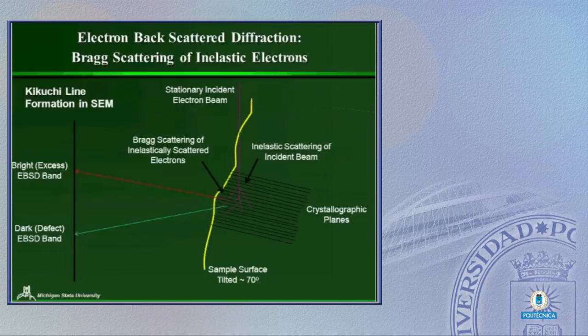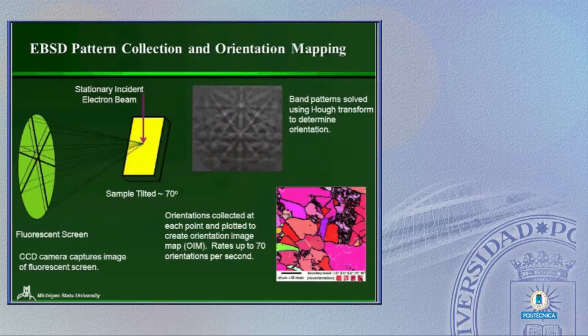So the idea with electron backscatter diffraction is we have a sample tilted to a fairly large angle. We have an incident stationary electron beam. We get inelastic scattering in the sample. And those inelastically scattered electrons diffract to form Kikuchi lines that we detect on some sort of a screen. And so the idea is you have a sample, again, that's tilted. We focus the spot on a given area. We collect these on a fluorescent screen, which then is recorded with the CCD camera. And we get patterns like this, which we can then use a Hough transform to determine the orientation.